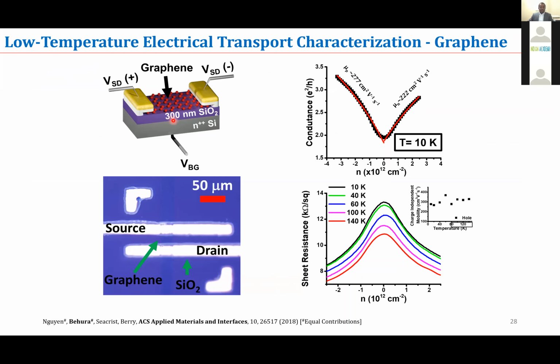So you have graphene, this is direct graphene on silicon oxide substrate, and we put metal as a source and drain, and we have measured the electronic mobility, which is about 270 centimeter square per volt second for the graphene sitting directly on silicon oxide without any transfer related steps. As you can see here, this is the small graphene structure, and we have metal as a source, another metal as a drain, and then we applied an electric field. Here we applied potential, we measured the current, and from the current and potential, we are able to measure the electronic mobility at very low temperature, 10 Kelvin.